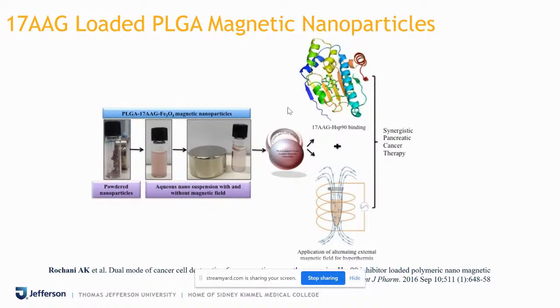So when you create a polymeric nanocomposite and you expose it to the magnet, it sticks to it and attracts towards it. This is a raw or layman way of understanding whether the particles that we synthesized had a magnetic component in them or not. And these powdered particles, when you put them in the aqueous phase, give a uniform aqueous solution that you can see on the screen.